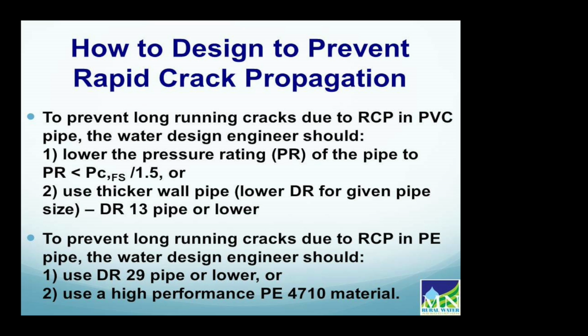So in summary, to design to prevent rapid crack propagation from occurring, to prevent these long-running cracks due to RCP in PVC pipe, the water design engineer should lower the pressure rating of the pipe such that the pressure rating is less than the full-scale critical pressure divided by 1.5, or use a thicker wall pipe, DR13 pipe or lower. To prevent long-running cracks due to RCP in polyethylene pipe, the water design engineer should use DR29 pipe or lower, or use a PE4710 material, and it'll never occur.